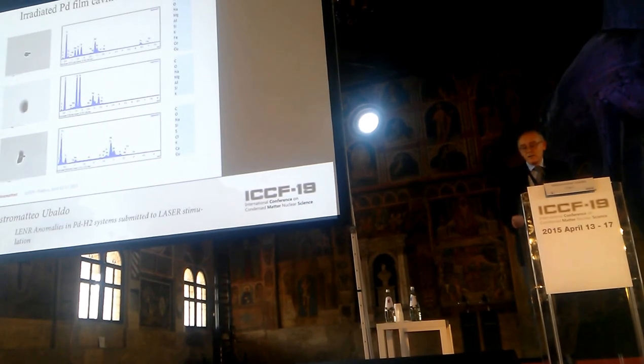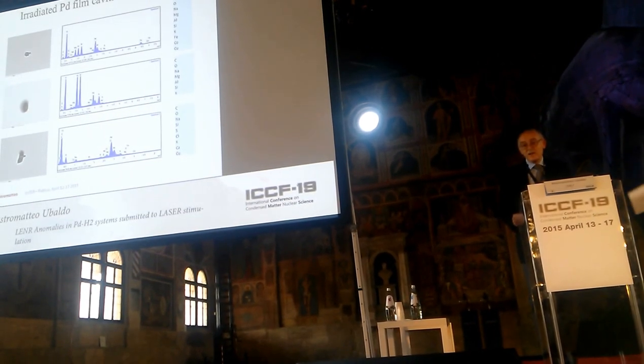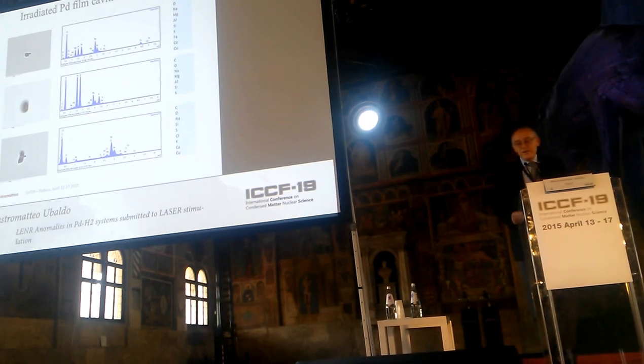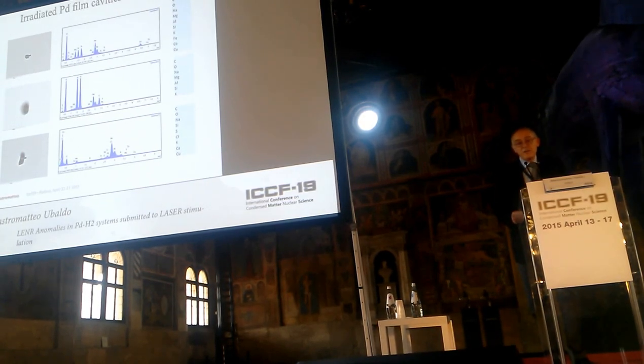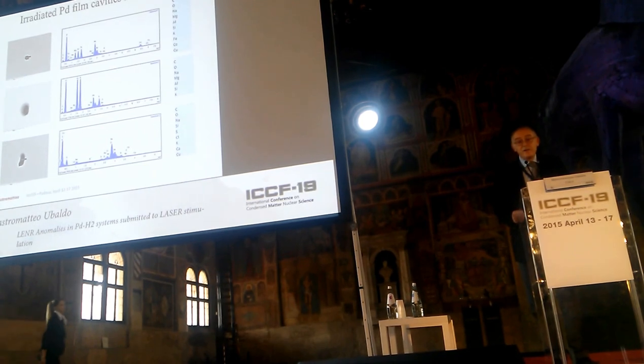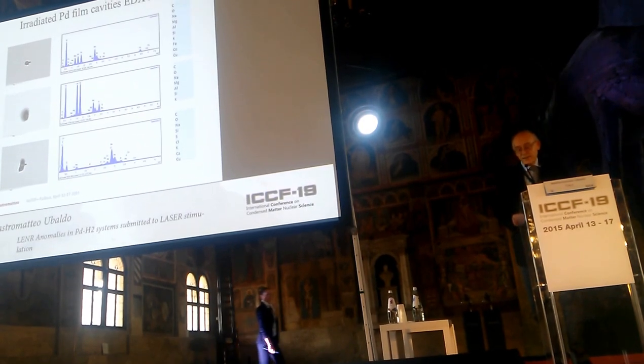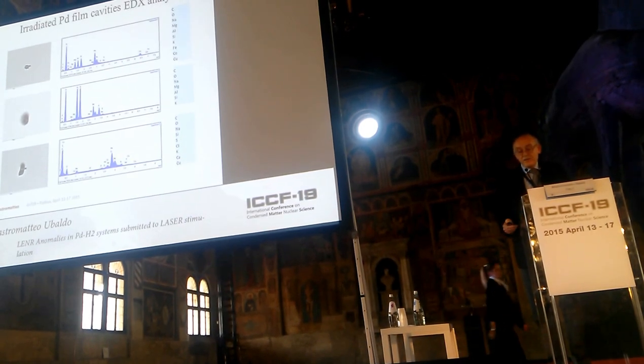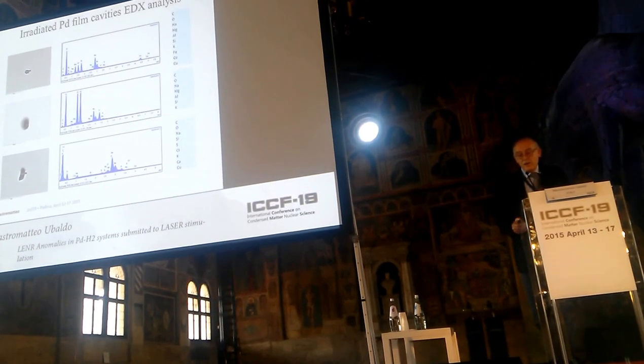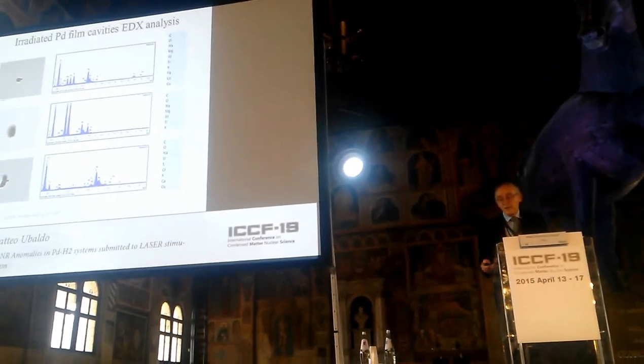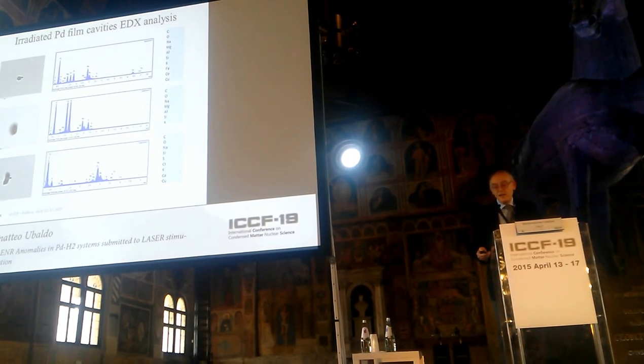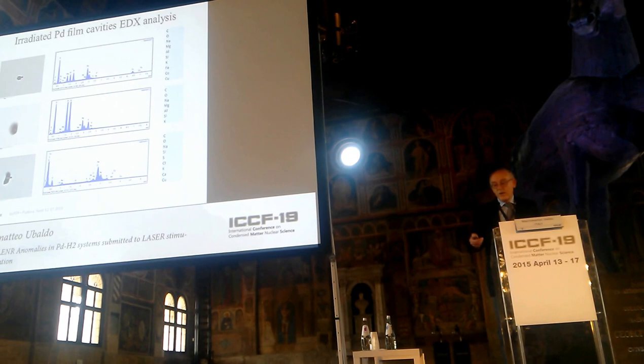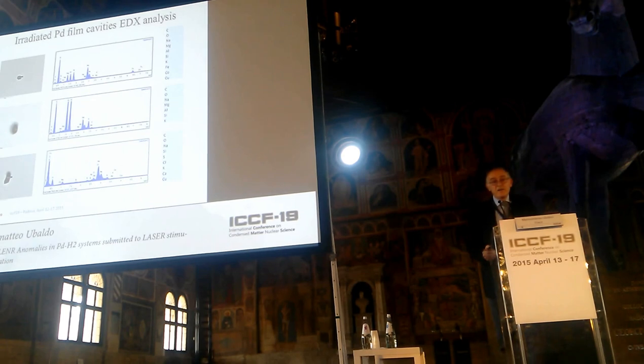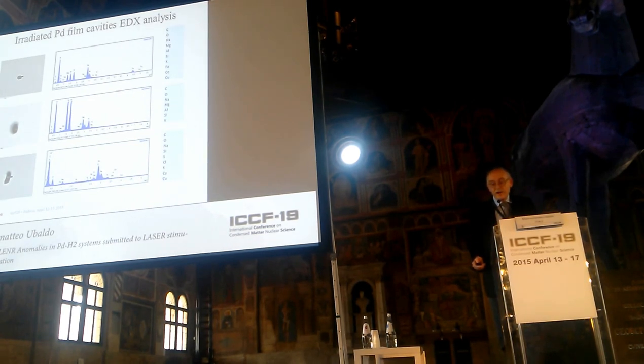So as we saw this morning, the texture of the surface of the palladium may be different depending on the substrate, chromium instead of titanium. We found many cavities on the samples after the experiment, and analyzing the cavities, we could find again elements very similar to the experiment I mentioned before as background.